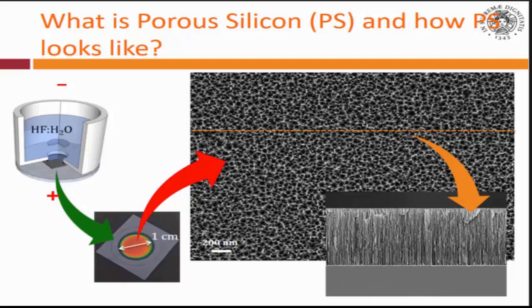By changing the porosity of the material — so by changing the mass of silicon removed per unit time — what you change is the refractive index of the material. This means you can really tune the material. This is why you see visible color, because this causes interference.